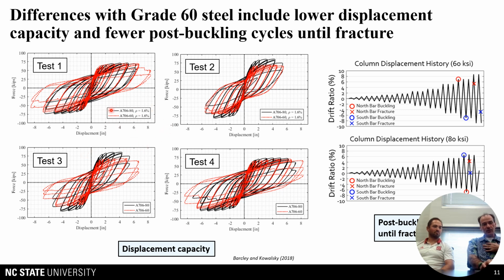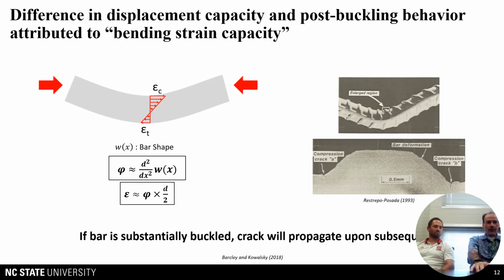And we noticed that overall, as you'd maybe expect, a slight reduction in displacement capacity, nothing drastic, but there was a reduction that was important to quantify. But the other thing that we noticed, which I think was more important, was over here, where we started seeing that in the case of the columns reinforced with the Grade 80 steel, there was not a lot of delay between buckling and fracture. It was almost like the next cycle, whereas in the Grade 60 steel, we'd always seen multiple cycles in between, and we thought that was important and interesting. Well, what's going on? Why is that different? And that's what led to this.